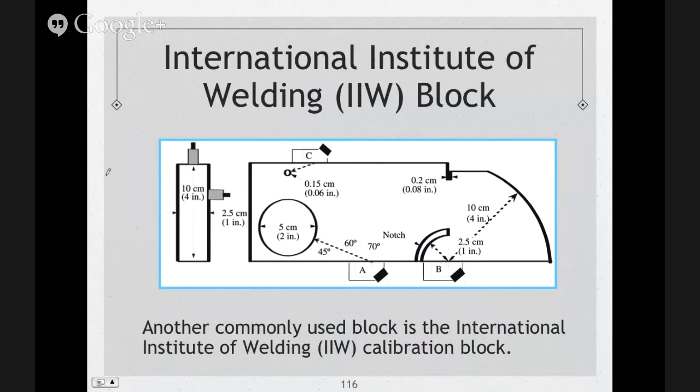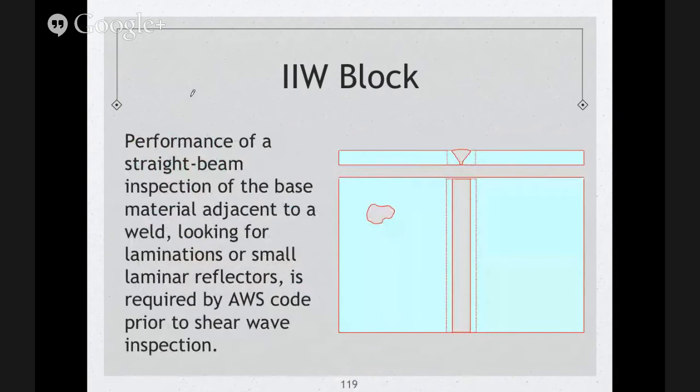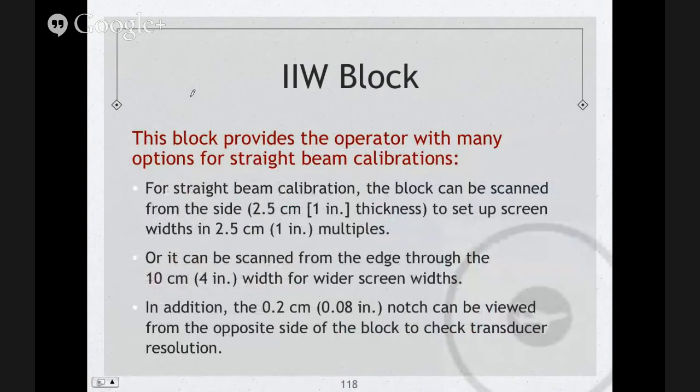your initial pulse, your 1 inch, and then you could also check the linearity of your equipment by seeing your echoes. Okay, and then increasing or decreasing your gain. Right. It can be scanned through the 10 centimeter width for wider screen widths. In addition, the notch can be viewed from the opposite side of the block to check the transducer resolution,